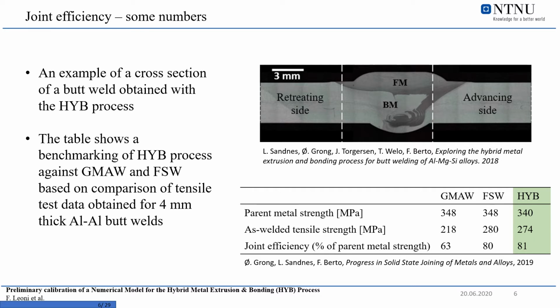And the table here shows also a benchmarking of this process against the gas metal arc and friction stir welding based on a comparison of tensile tests obtained for 4 millimeters thick aluminum butt welds. And as you can see here, the process is capable to compete with those widely used technologies.